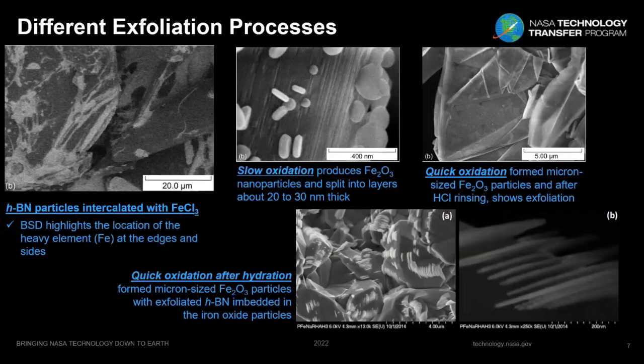see them embedded with separated layers, but embedded in the iron particles, big particles. So the other image is a zoom in of an area where you can see the separation of the layers. They are very small, thin layers, and they are separated. I really love seeing this micrograph because it shows exactly what this process does and the different ways that you can exfoliate these samples.